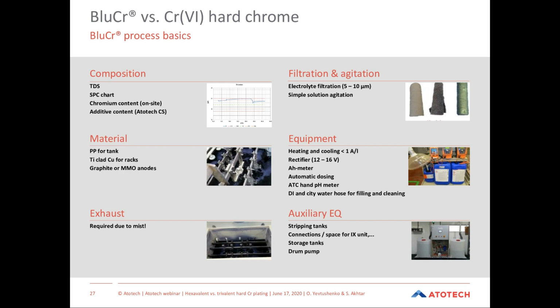If we compare material, as Shakil already mentioned, for blue chrome you don't need to go for expensive PVDF material for the tank. You can just use PP, it works fine. Then again, you can use inert graphite or MMO anodes. For hexavalent, we know that you need to use lead. For the blue chrome process, however, it is required to use titanium clad copper for the cathodic and anodic bars. That is not the case for hexavalent, where you can also use copper.